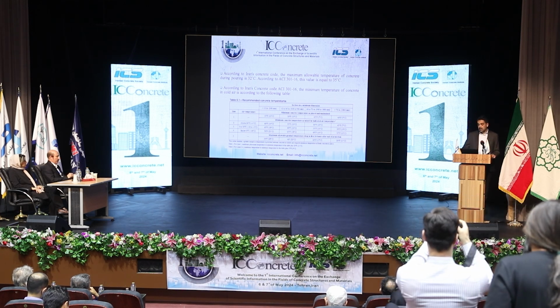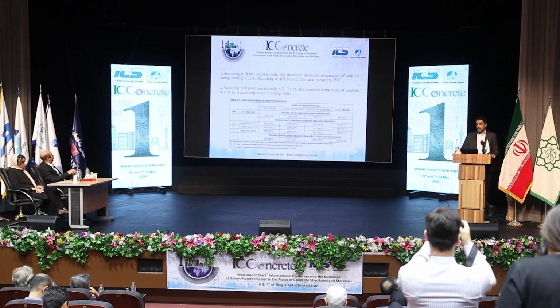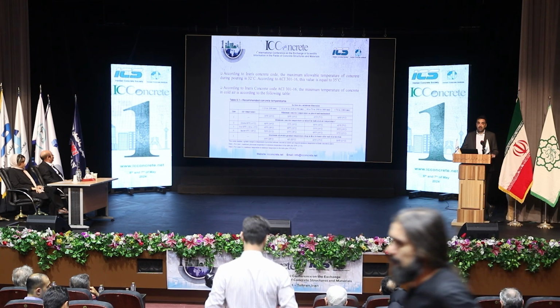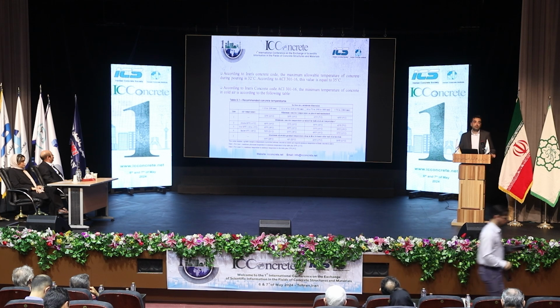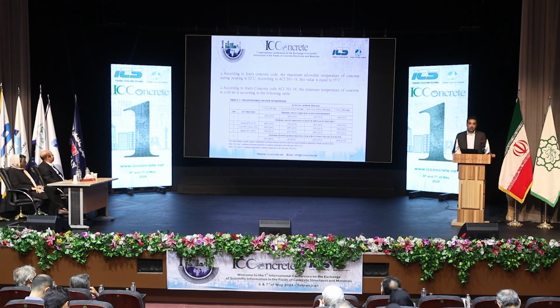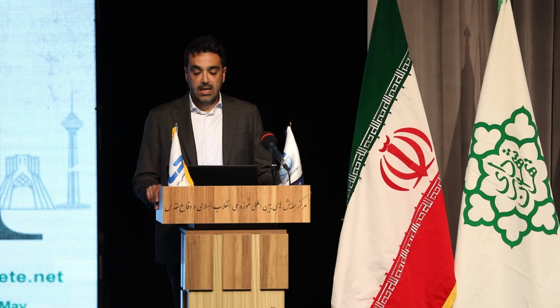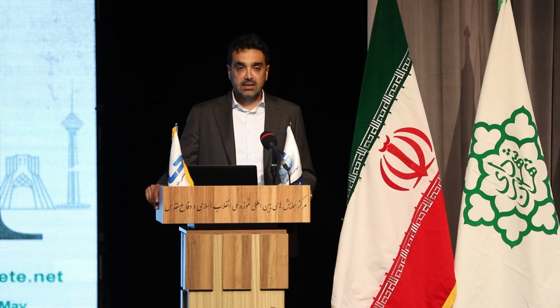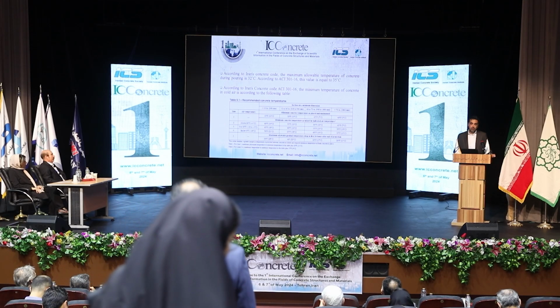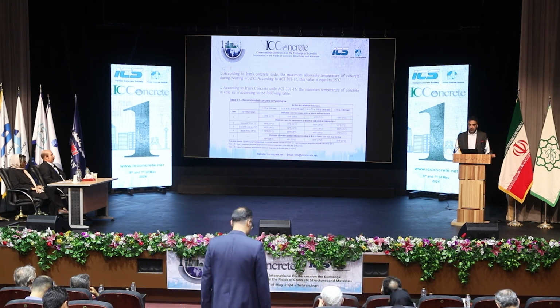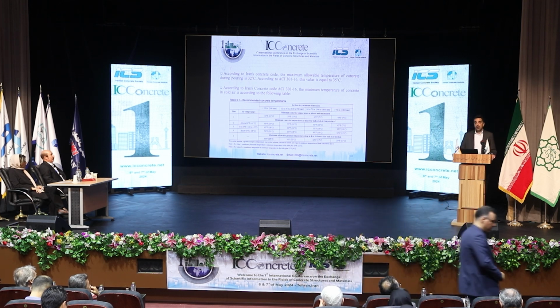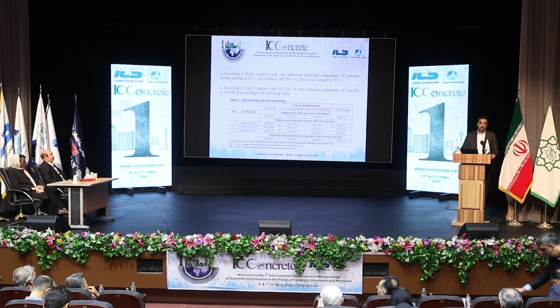In the Iranian concrete code, we assigned 32 degrees Celsius for the maximum temperature of concrete. Nevertheless, in ACI 301, it has been assigned as 35 degrees Celsius. As you can see, our codes are more limited. And for cold weather concreting, our code is almost similar to the ACI code. The minimum concrete temperature is a function of the thickness of our concrete elements.